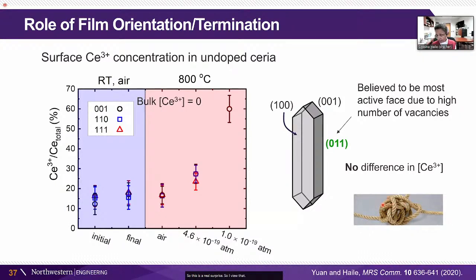I view that there's a knot here in terms of understanding what's happening with the surface of ceria. We're starting to unravel this knot, that it is not a simple relationship between the vacancy concentration on the surface and the catalytic activity. Certainly, there's no simple relationship between the vacancy concentration on the surface and the termination, as was predicted.